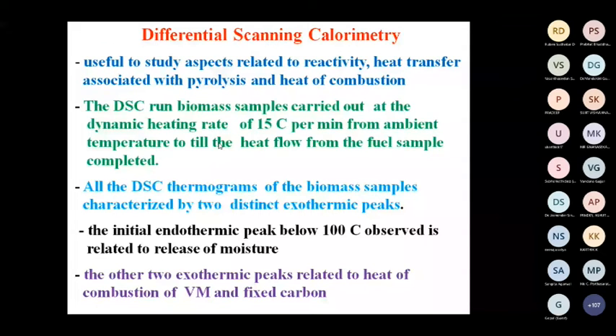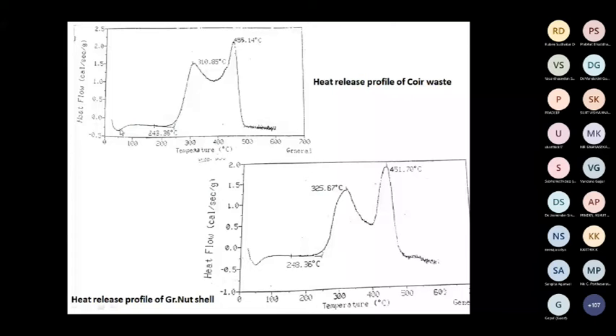The initial endothermic peak is observed below 100. It relates to the release of moisture. The other two exothermic peaks relate to the heat of combustion of volatile matter and fixed carbon. You can see here, this initial endothermic peak is due to removal of moisture, whereas these two exothermic peaks are related to combustion of volatile matter and fixed carbon. So this is the heat release profile of coir waste, and the heat release profile of groundnut shell.